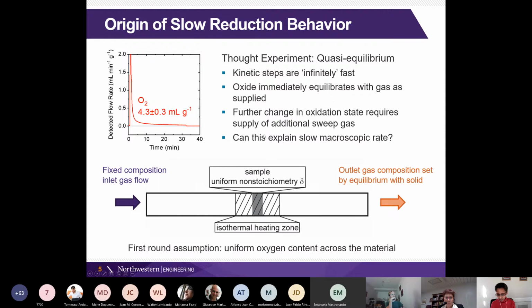So here's our thought experiment where we have this fixed composition inlet gas. And what we're doing is imagining that the outlet gas composition is set by equilibrium with the solid. So we have a first round assumption to be able to model this, which is that there's a uniform oxygen content across the entire material here. So everything is in equilibrium here. The new piece comes in and changes everything till we get to the next state of equilibrium. So that means we need to understand the equilibration behavior of the solid.